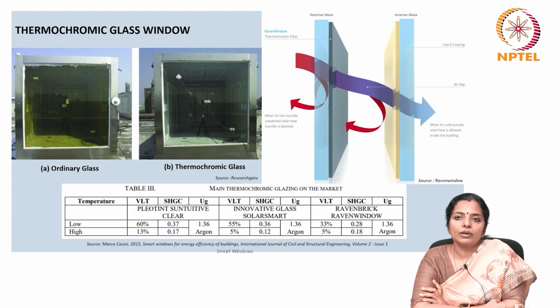As PVB is commonly used in laminated safety or acoustic glass production, this solution integrates seamlessly into manufacturing processes, providing a cost-effective, high-quality product. Paired with clear glass, the typical light transmission and solar heat gain ranges in transparent and opaque states are VLT as 60 to 13% or 55 to 5% and SHGC as 0.37 to 0.17 or 0.36 to 0.12 with switching times in the order of a few minutes.